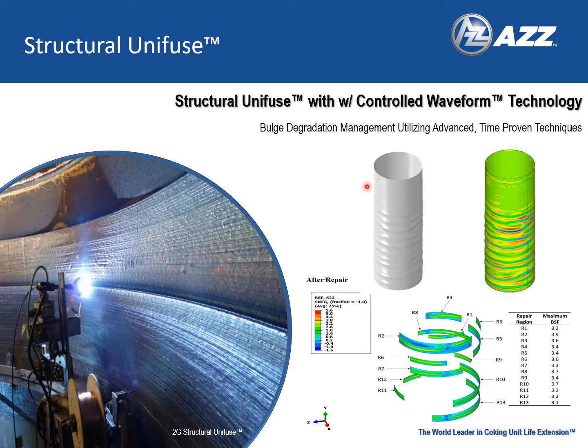The basic approach starts with measuring the as-deformed vessel geometry by laser mapping. This geometry is used to generate a representative finite element model of the vessel. The model is then exposed to loading conditions created by the specific operating cycle of the vessel, and with this and other loading conditions, the bulge severity factor for the drum is calculated. Areas with high bulge severity factor will show more rapid degradation.